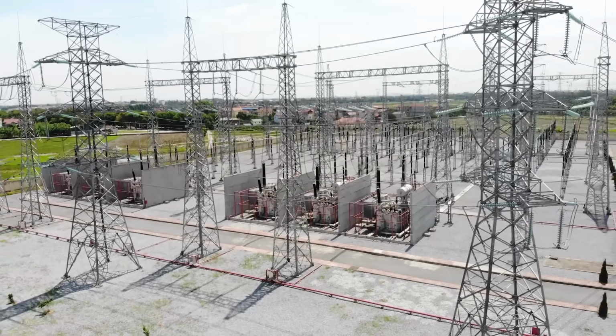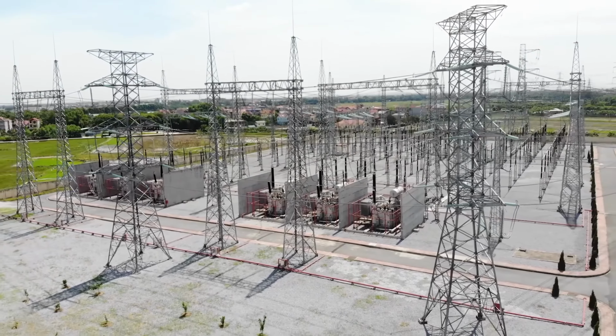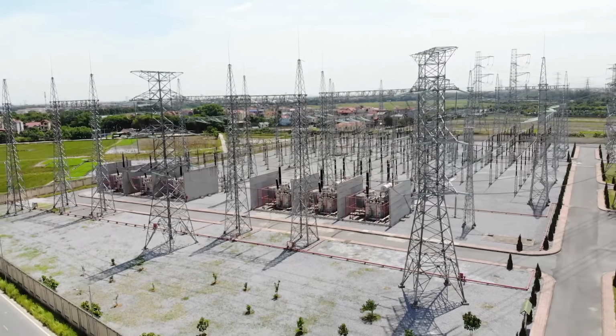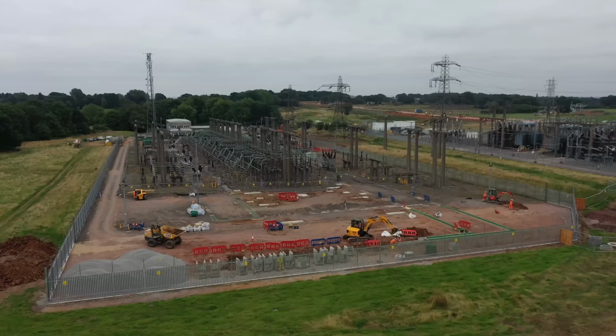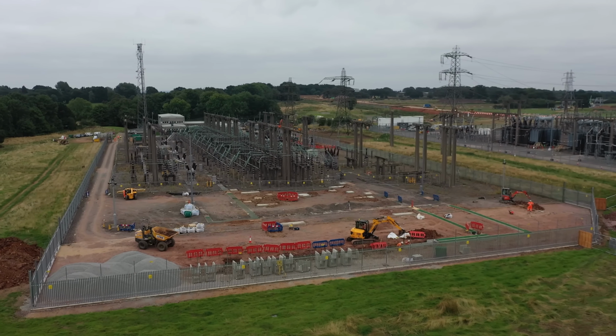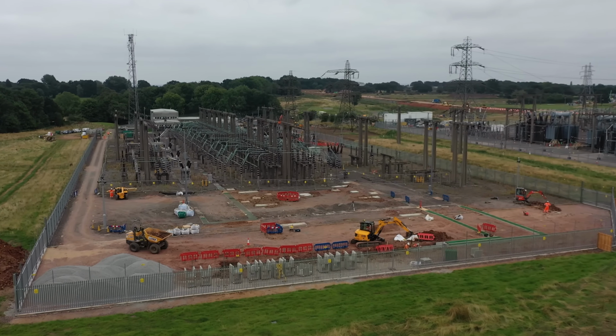Two other crucial problems for aluminum are creep and its higher coefficient of thermal expansion. With the temperature variations caused by the flow of current, aluminum expands and contracts more than copper. This constant movement, combined with creep, which is a slow plastic deformation that occurs under continuous load, even below the yield strength of the material, causes aluminum connections to loosen over time. And loose connections are synonymous with increased resistance, overheating, and high risk. Aluminum is also more prone to galvanic corrosion when in direct contact with metals like copper.